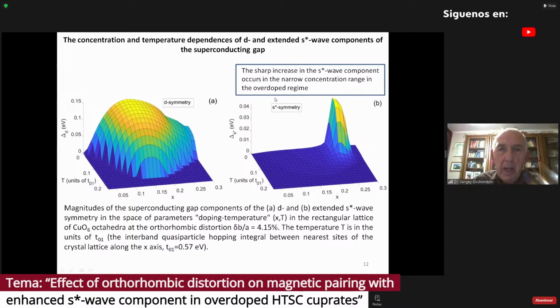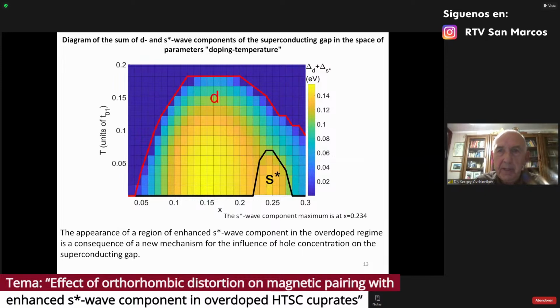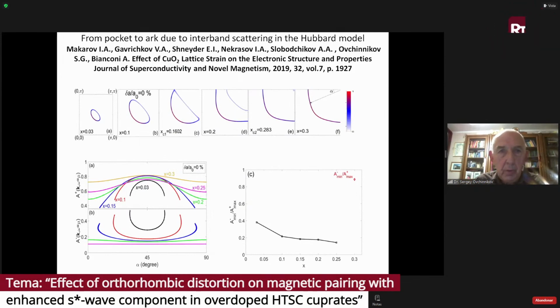Okay, I will continue. So on the slide, I show the large gap, D-wave, and smaller gap, S-star gap. And the total gap given by a sum of D and S-star gap is shown here. Of course, S-star gap is smaller than the D-wave gap, and it appears only for the large doping, around 25% of doping. And it exactly corresponds to the gap found in overdoped cuprates. Well, here I show the evolution of the Fermi surface with doping.